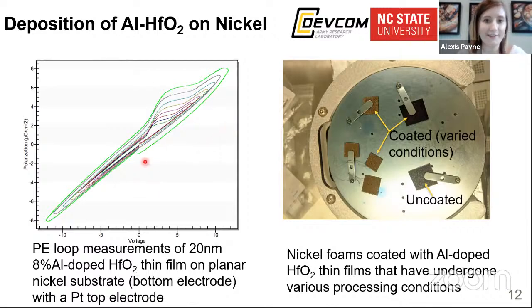On the left, you see a polarization electric field loop of aluminum doped hafnia on planar nickel. It is 20 nanometers thick and 8% doped. And you can see we're having a linear dielectric-like response with an interesting hump here, which we believe is due to charge build up at the electrode, one of the electrode interfaces.